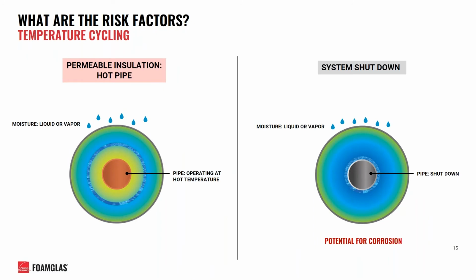Similarly, we can take a look at what happens to permeable or poorly installed insulations on hot pipes that operate above 350 degrees Fahrenheit or so. If moisture is allowed to penetrate the system, liquid water near the surface of the hot pipe will boil off as vapor. This can, in a sense, force any liquid water present away from the pipe, where it often settles within the insulation itself at some thickness.